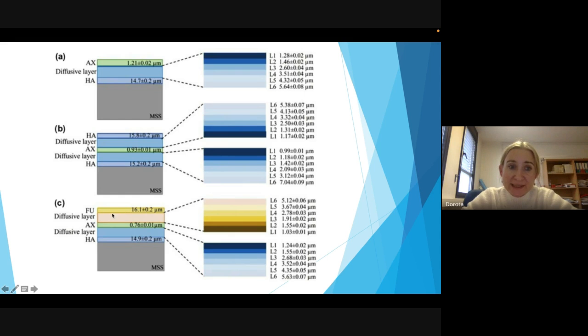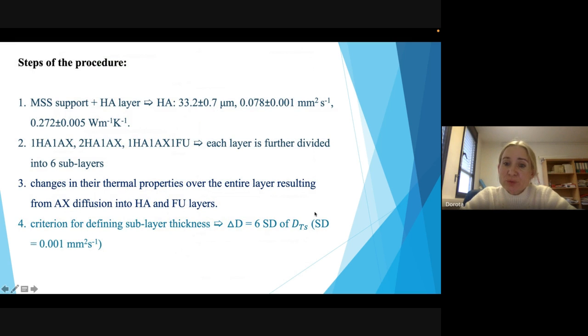We introduced another diffusive layer in our theoretical model, and all the diffusive layers were further divided into 6 sublayers. So we performed multi-parameter fittings to determine the thickness of each sublayer and their thermal properties. The criterion for finding the thickness of such a layer was 6 times the standard deviation of the thermal diffusivity that was determined for only the hyaluronic acid layer.